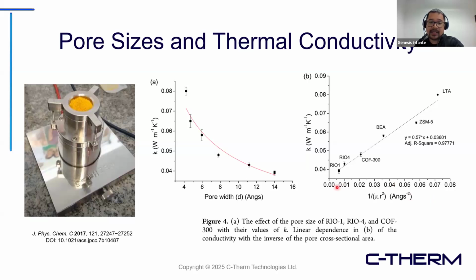cross-sectional area, you can see that it's very linear, and again, a very strong indication of that. Which kind of makes sense if you really think about it. A larger pore size: as you're increasing the pore size right here, you're decreasing the thermal conductivity as a whole, because now you have a larger void space, and then you're decreasing the density of your material, which creates less pathway for phonons to transfer within the system.